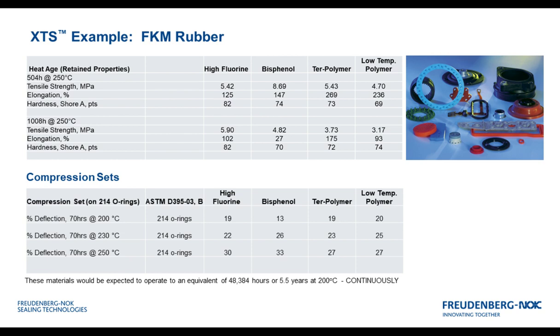In addition, one can see in the upper right chart that the retained properties are very good even after 1,000 hours at 250 C, which is defined by SAE J2236 as the continuous upper temperature limit for elastomeric members. The flexibility and hardness is measurably good. So these materials would be expected to operate continuously at very high temperatures.